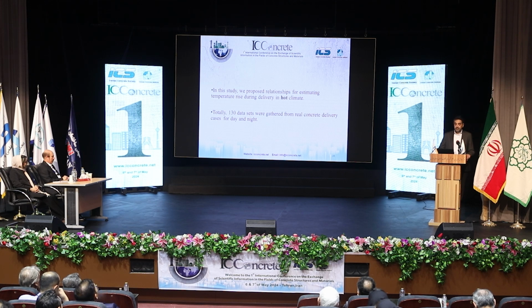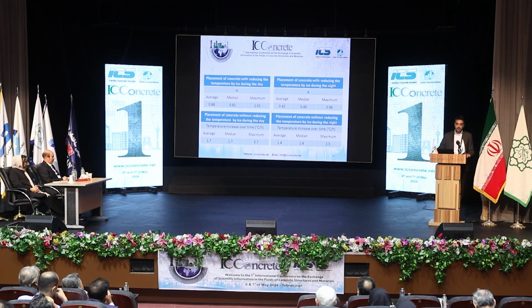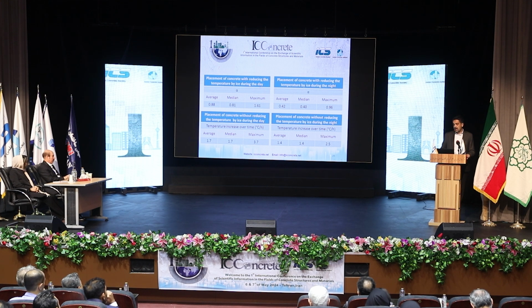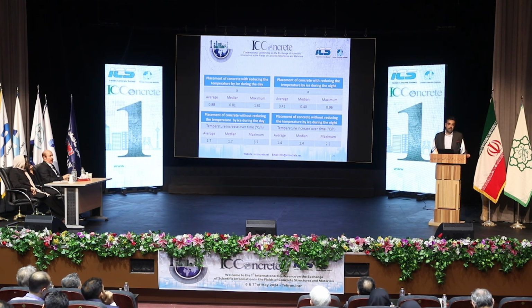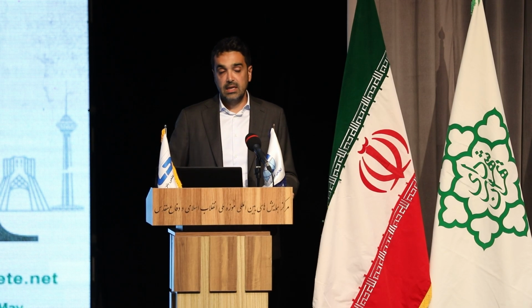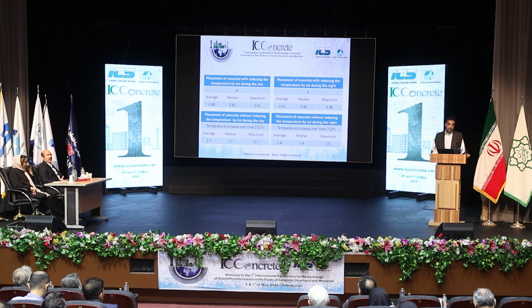Our results are obtained from about 130 data sets in real concrete delivery. We presented 4 tables for estimating the concrete temperature in hot weather concreting during delivery of concrete. We proposed alpha constant for that formula presented by ACI separately for the night and day. When we reduce the concrete temperature with ice in a day, we reached the average of 0.88 for alpha constant, and for the night it was 0.42.